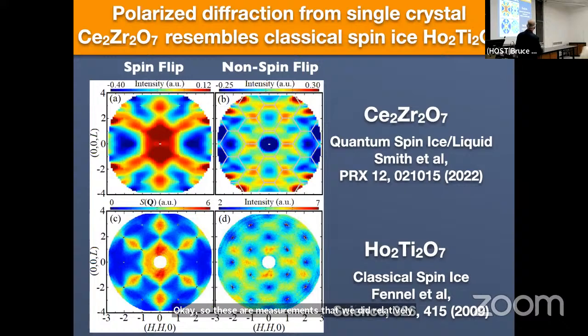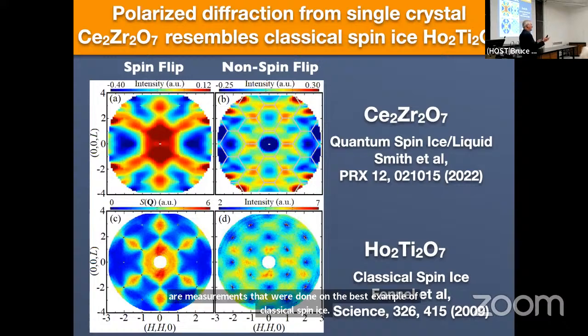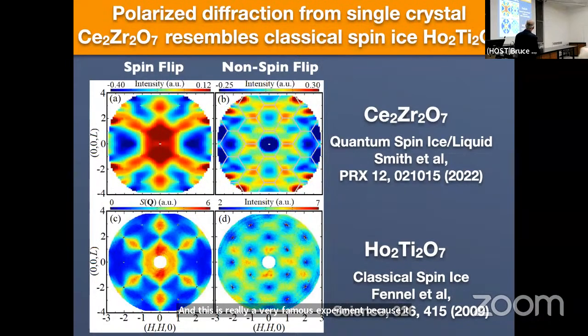These are measurements that were done on the best example of classical spin ice from about 15 years ago. So with classical spin ice, the quantum numbers are much bigger, the magnetic moments are much bigger, much easier experiment. You have much more intensity to work with. And this is really a very famous experiment because it shows these pinch points very, very well. And it also shows this diffuse scattering that goes around the zone boundaries of the FCC lattice.